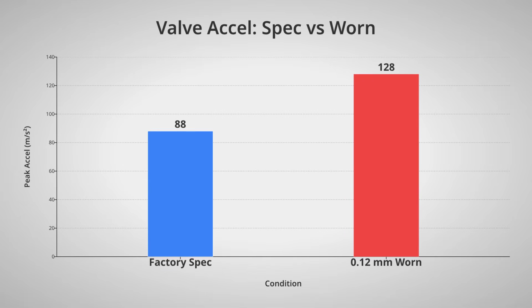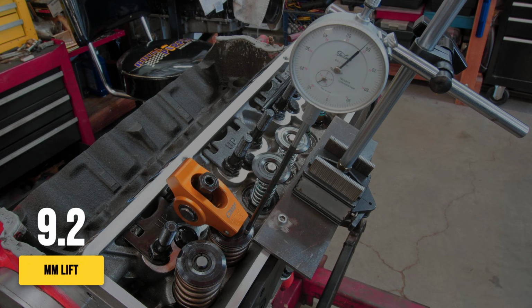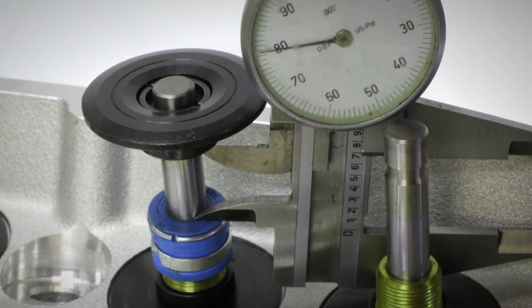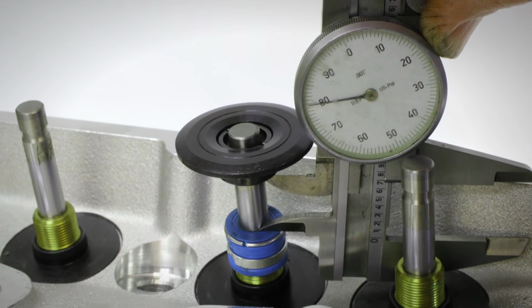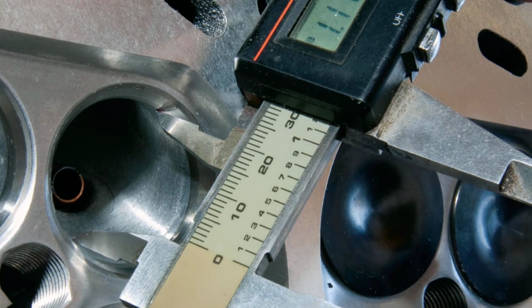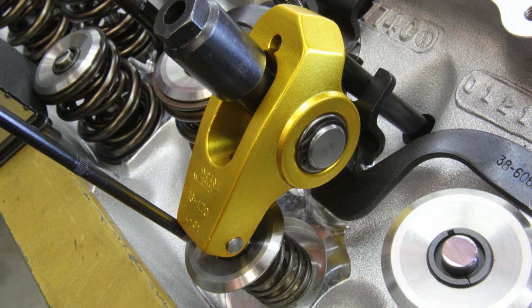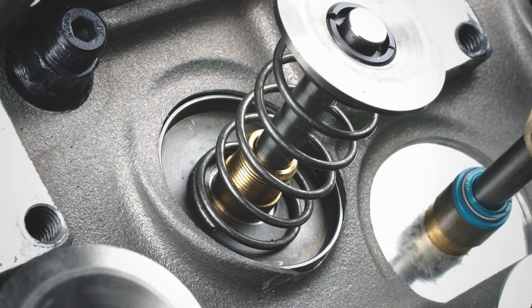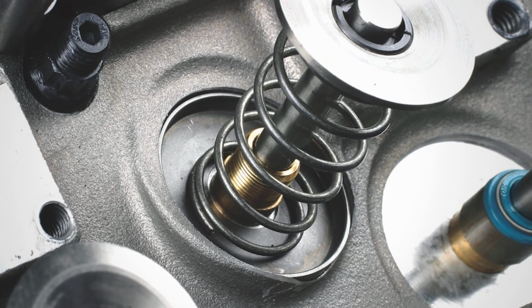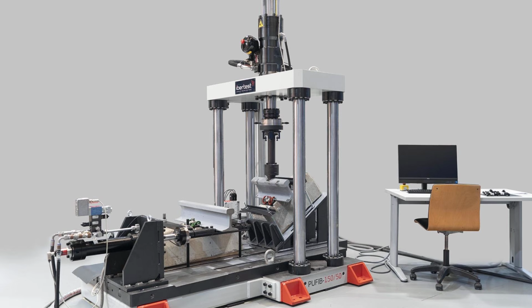As the pivot geometry degrades, the valve acceleration spikes. The measured lift, once 9.2 millimeters, now registers 9.7 millimeters. That extra half millimeter is not a harmless tolerance. It multiplies the inertial load on the valve keeper, forcing the 2-ounce clip to absorb impact energies far above its tensile yield limit. The keeper is now exposed to both increased axial shock and lateral deflection.